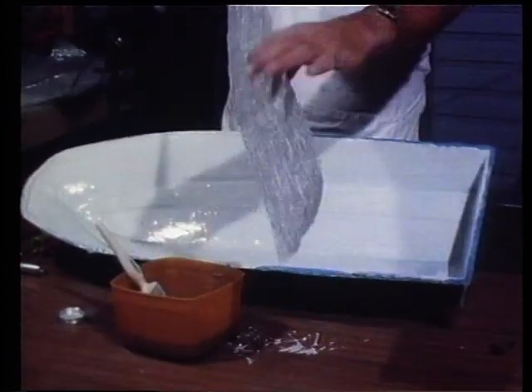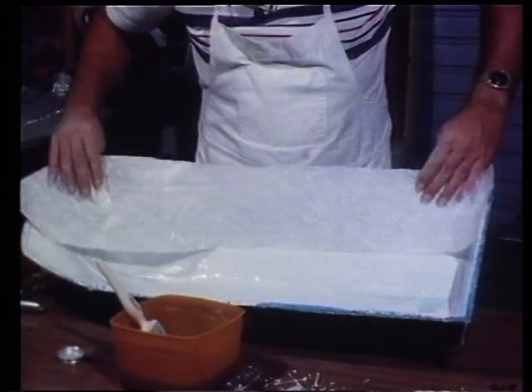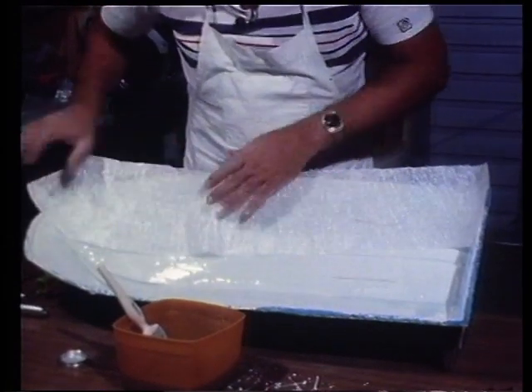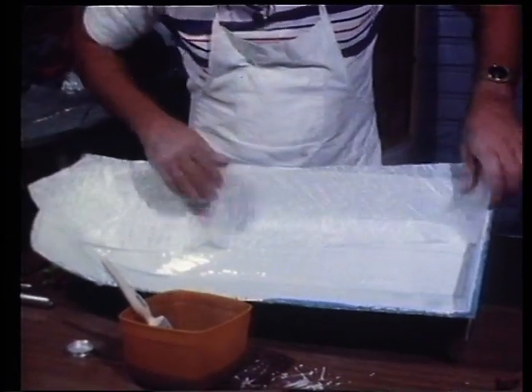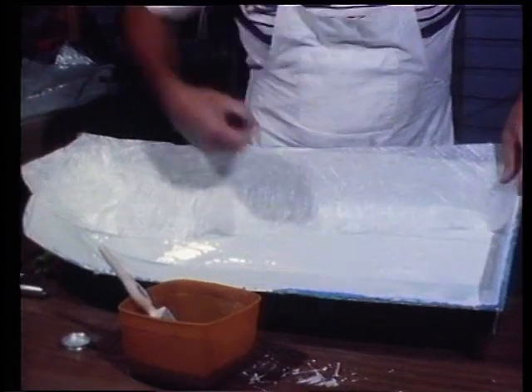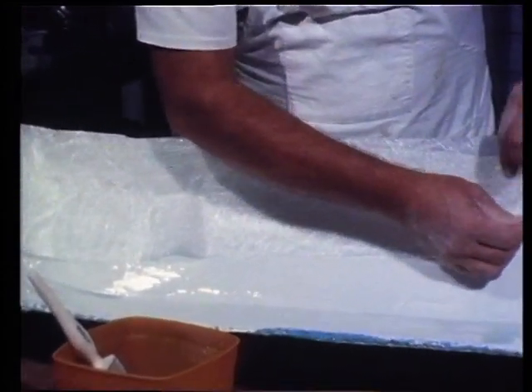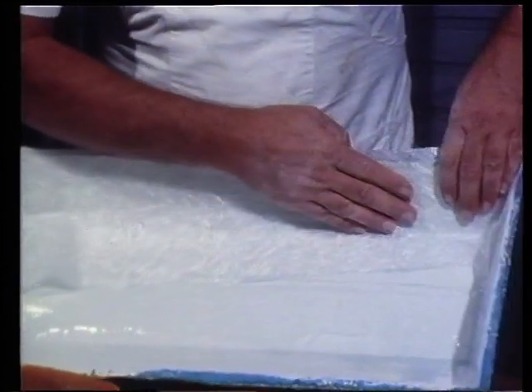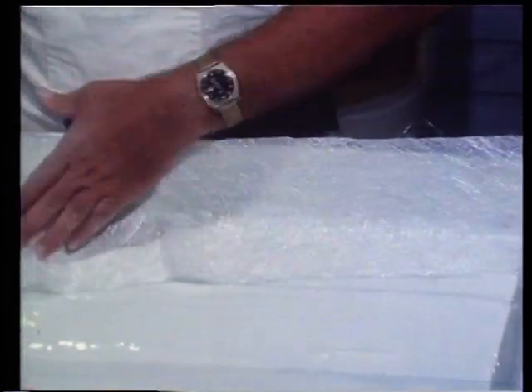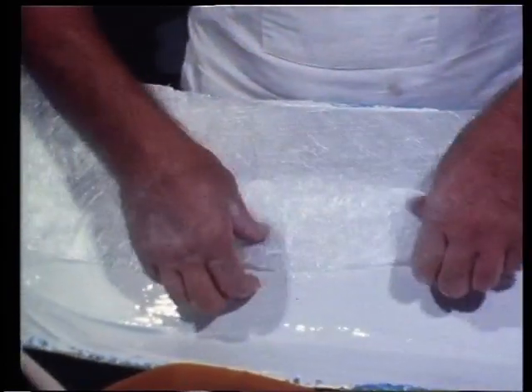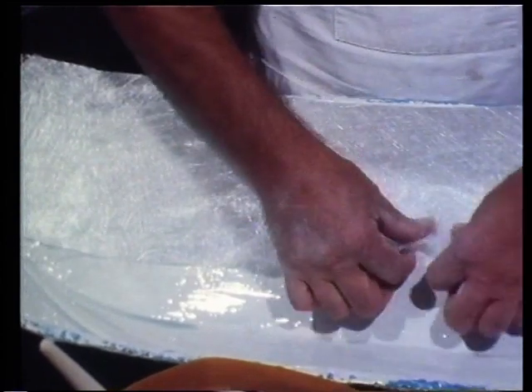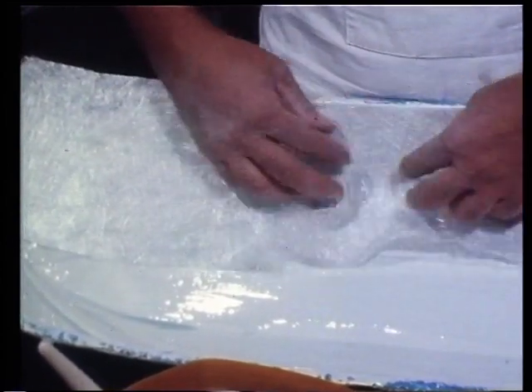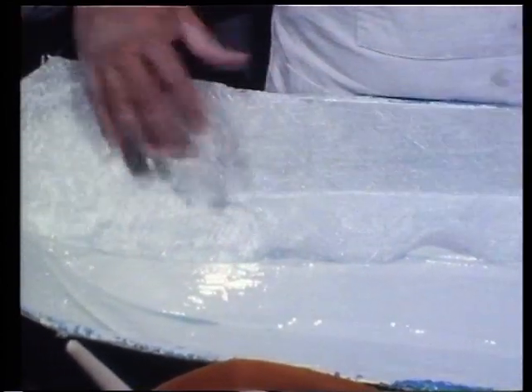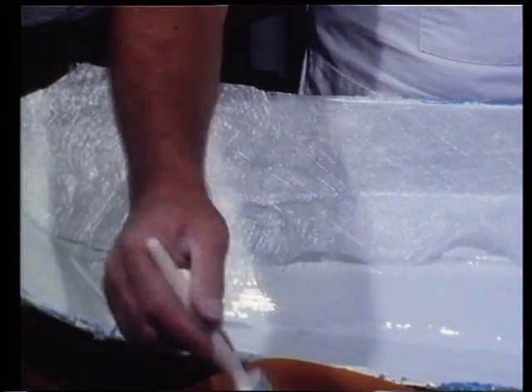Now, I've pre-cut this glass with the scissors so that it approximately fits into that mould in the shape that I want it. Now, I find that it is folding up here, so I'll just tear the chop strand mat in that corner so that it settles down. Make sure that the glass is settled down properly into all areas of the mould. If I see that it's folding up, that it's bubbling there, I can just quite happily tear it and it will settle down into the mould.